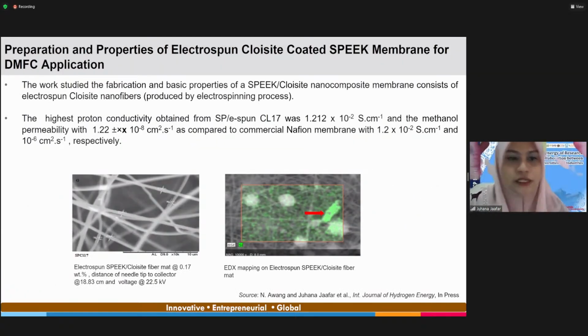All right. So the issue has initiated us to conduct this study: preparation and properties of the electrospun Cloisite nanofiber coated SPEEK membrane for the DMFC application. To be honest, this is not a recent study that we've conducted, but I really like to share this achievement because the structure itself is very unique when we have the Cloisite nanofiber in our SPEEK membrane. The SPEEK is the polymer matrix and the Cloisite clay is the inorganic material that we use as the additive in this study.